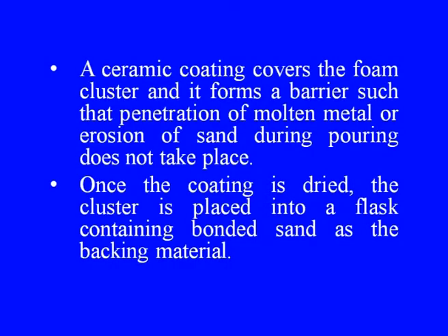A ceramic coating covers the foam cluster and forms a barrier such that penetration of molten metal or erosion of sand during pouring does not take place. Once the coating is dried, the cluster is placed into a flask containing bonded sand as the backing material.